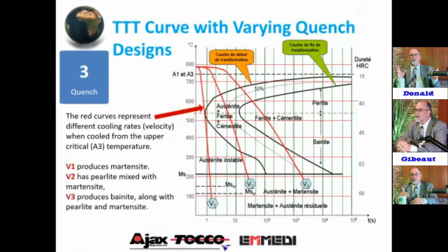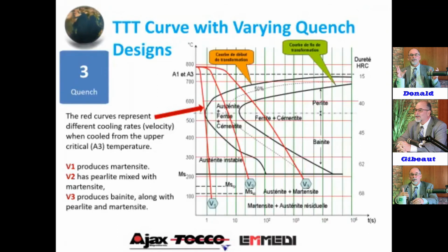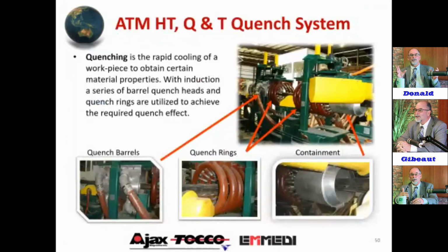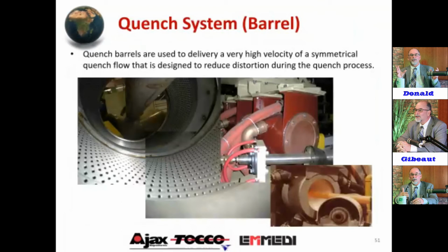Now, this is just another show of time and different points for different grain structure mixes as you increase the time it takes to quench out. And again, you get a mixture of pearlite and martensite in the grain structure or bainite, and it's just not desirable results. And that's what you get out of non-aggressive quench systems that don't consider that TTT curve and understand the aggressiveness that's required of this quench. So the quench that we made aggressive to the TTT curve is made up of barrels and rings. And again, these barrels, like I said, have small diameter holes, and that's where the primary work is done.